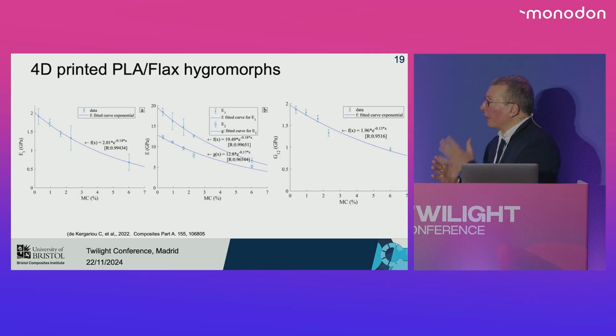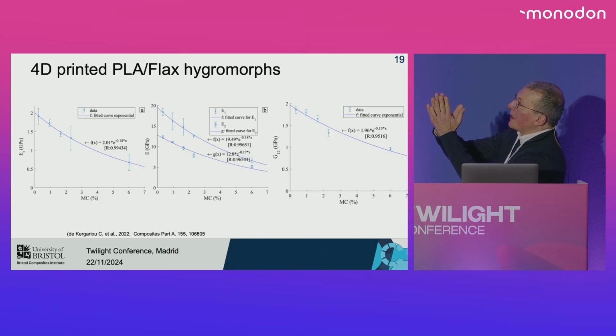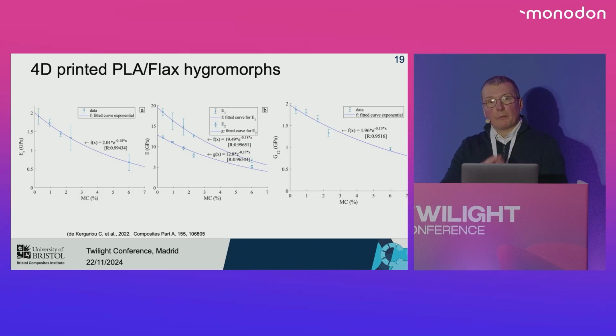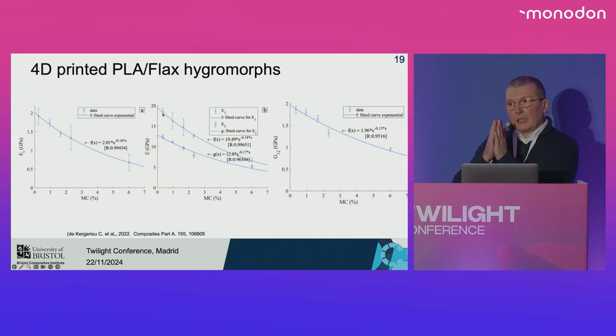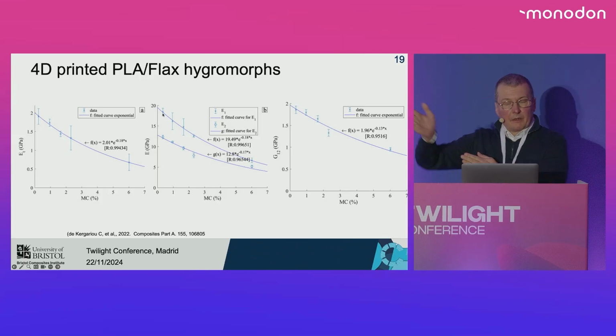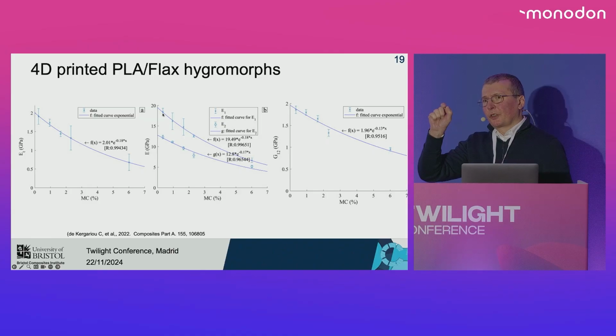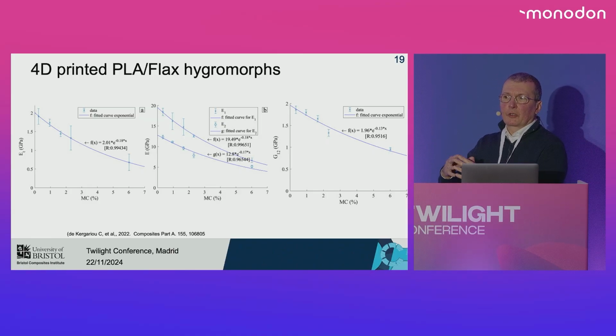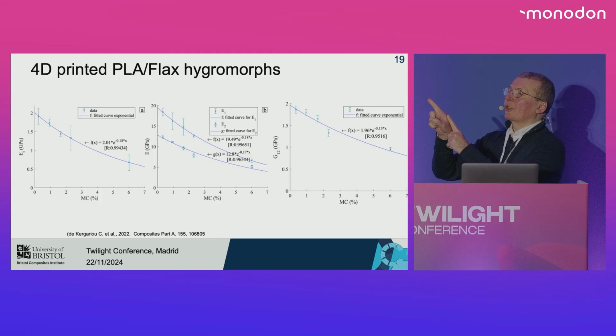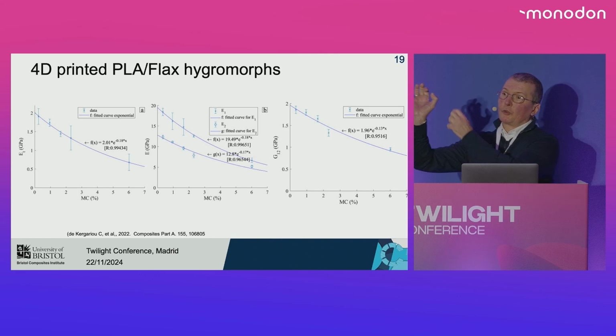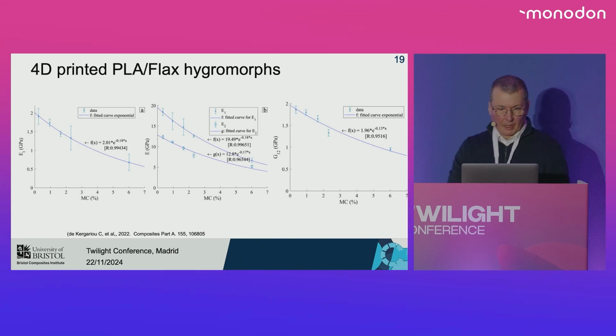And just to give you an idea how their stiffness evolves with the moisture content or relative humidity, in the longitudinal direction, over there you see two different Young's moduli. In general, in this kind of natural fiber composite, you have almost a sort of bilinear type of behavior under tension. So we take really two moduli to give this indication of stiffness.